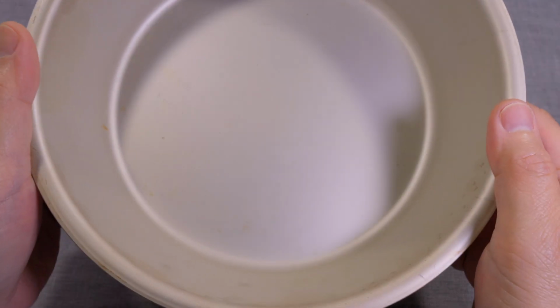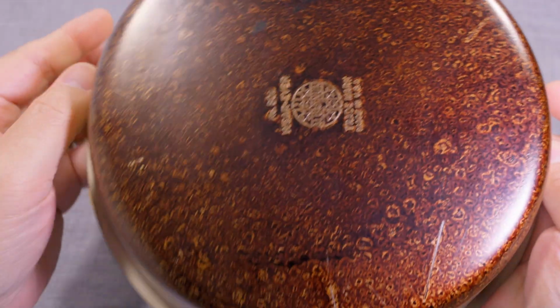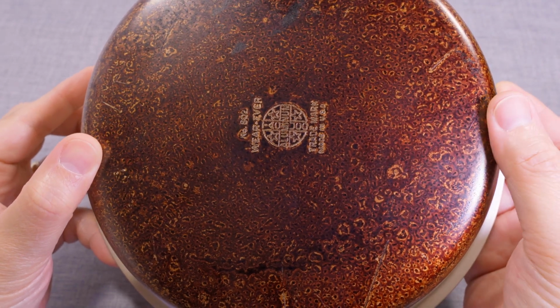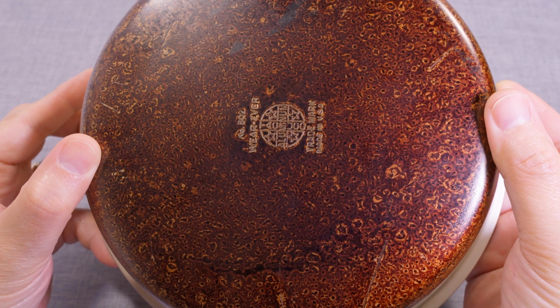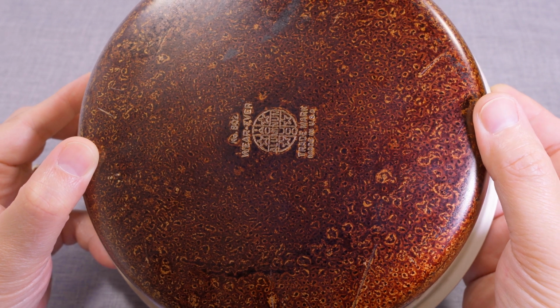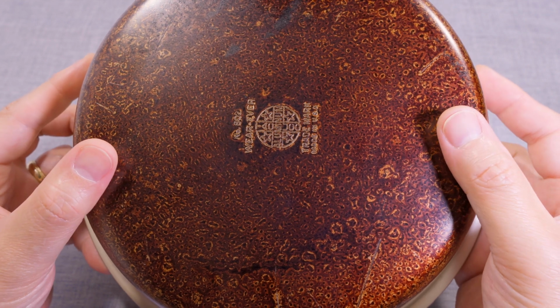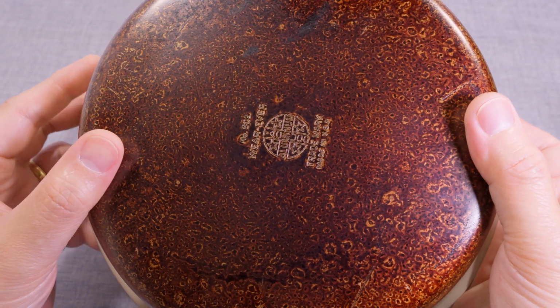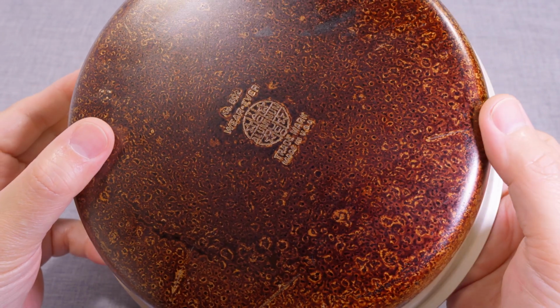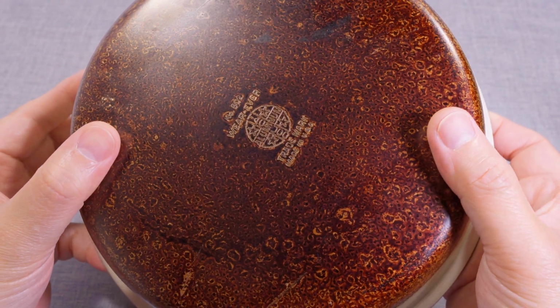oil. For this test, I used this aluminum pie pan, one of my old pans, which is not anodized. This was after 6 layers of grapeseed oil, 500 degrees for 1 hour for the first 5 layers, and then 500 degrees for 3 hours on that final layer. This last layer, though, I started at 1 hour, but decided to see how far I can push it, and I added 2 more hours to it. No additional oil. As it should, with each consecutive hour, it became darker as the oil carbonized.